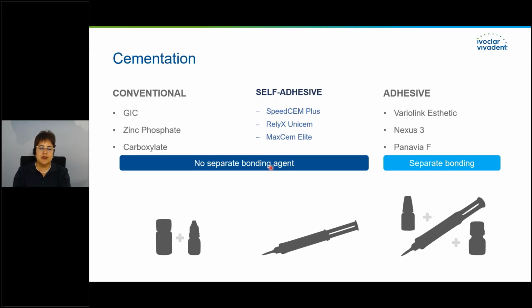The main difference between the conventional, self-adhesive and adhesive luting protocols is that we need a separate bonding agent or primer for the adhesive luting protocol. On the other hand, conventional and self-adhesive protocol don't need a separate bonding. The self-adhesive cement contains an agent which is called MDP, which will create a chemical bond towards the tooth and towards the restoration surface. Therefore, it is easier to apply.